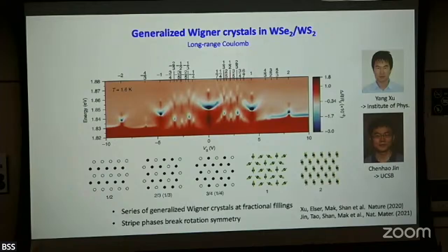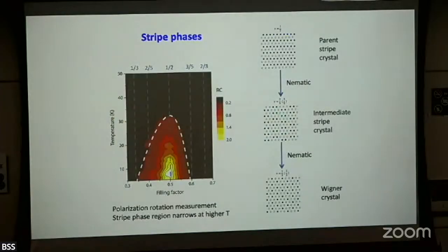So if you have a sensitive optical anisotropy measurement, you will pick up this birefringence. And you can also determine the direction of this linear chain. And you can map out, in your sample, you have domains, chain along this way and that way, and that can also be done. So I just want to show you